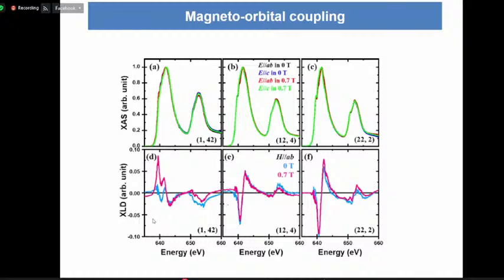This is the result of XLD. Maybe someone is familiar with this tool and others are not. XLD is a tool to see orbital structure in films. We use X-rays with polarization, so depending on the polarization direction, the amplitude of interaction is different. We used different kinds of polarization, then we get the differences between two different polarizations of X-rays. From this, we can know the orbital structures.